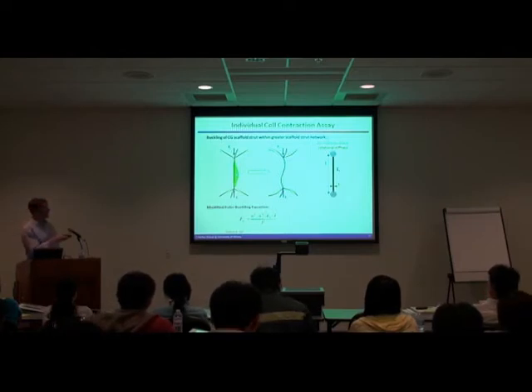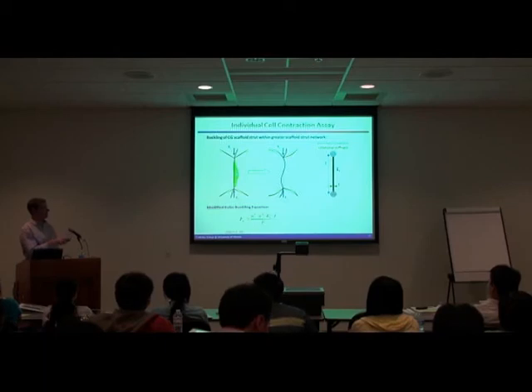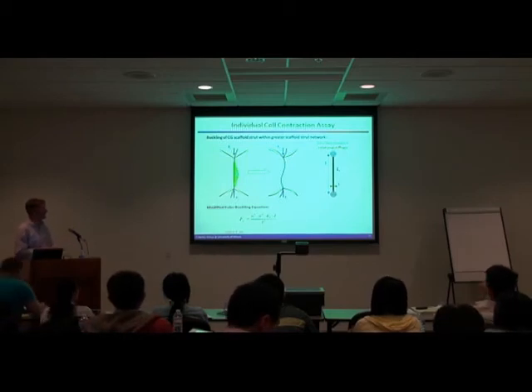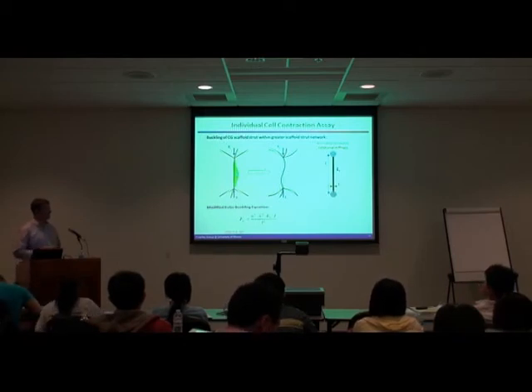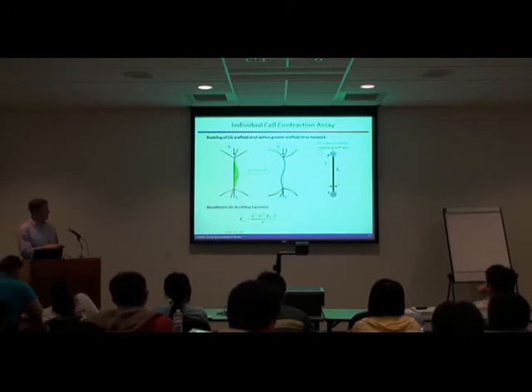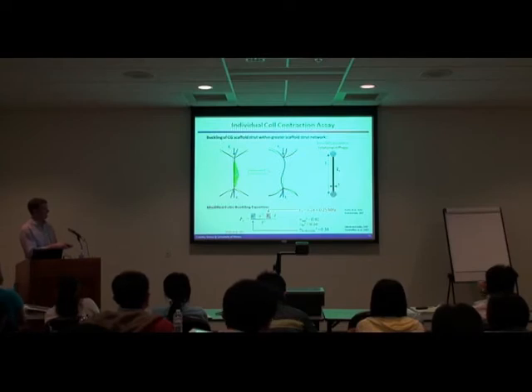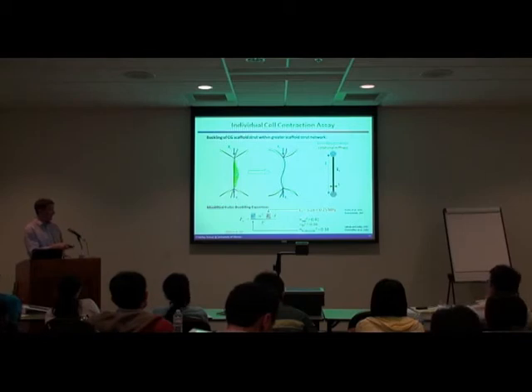So what you're seeing here is an individual fiber that's buckling, but it's not like it's pinned at either edge. Either end of the fiber is actually attached to the much larger scaffold structure surrounding it, so it's almost a rotational stiffness that's associated with the scaffolds is the way you model it. And so what you can do is actually generate measurements of contractile force generated by individual cells based off of the modulus of the strut of the scaffold, which we've measured experimentally and confirmed using a modeling theory, and a prefactor that's based off of the type of contraction you're seeing, whether it's single direction, multi-direction, or more of a hydrostatic type contraction.